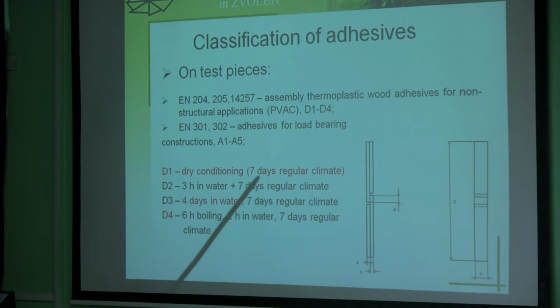conditioning after 7 days in regular climate. Regular climate is 60% of humidity and 20 degrees of temperature, room temperature. And another set of pieces we tested after 4 days immersed in cold water, and we tested the shear strength. All results you have, and you will evaluate them maybe today.